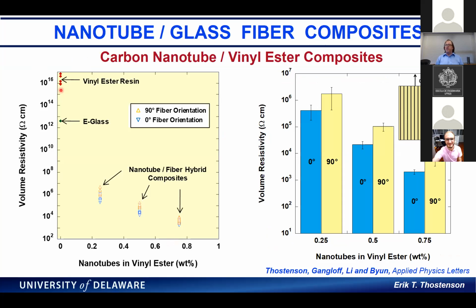So here, this is just showing, very similar to the nanocomposite, the electrical percolation. We have the basically insulating vinyl ester and glass, and then when we add the nanotube to the matrix, we can significantly change the electrical properties, and that's really what enables our sensing approach. What's interesting is that they're also a little bit anisotropic, partly because of the structure of the fibers: in the longitudinal direction, the percolating pathways go along the fibers, and in the transverse direction, they go around.